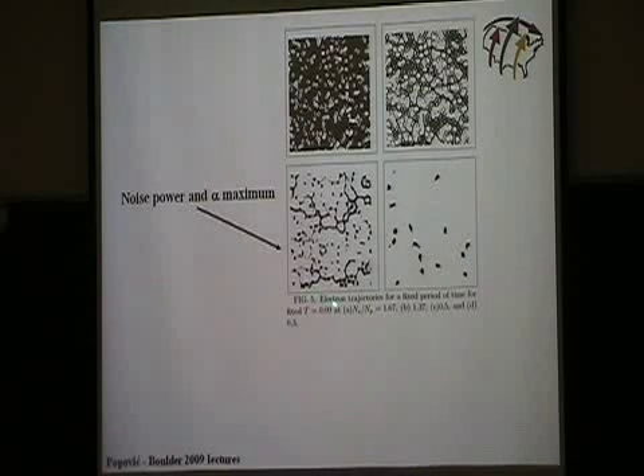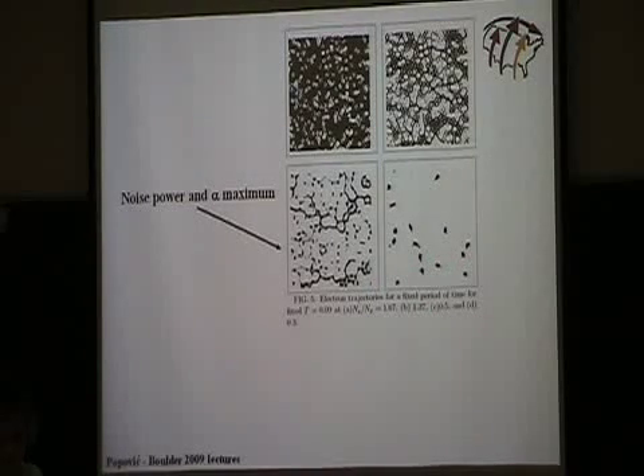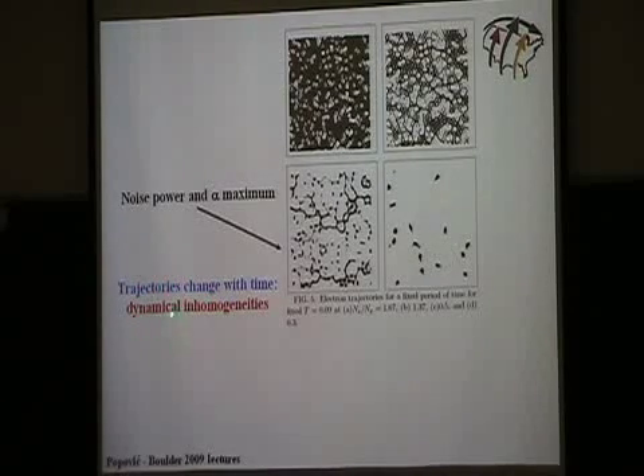And as those of you who work on such things know, they can obtain, if you look at electron trajectories for a fixed period of time, so this corresponds to the case when you have a high density of electrons. You can see that electrons can more or less move freely throughout the sample, except that some may get stuck for a while somewhere, but essentially they can flow easily. As you reduce the density, this splits into a kind of mixture of 2D, 1D paths. And at even lower densities, the motion is mostly through 1D channels. Other electrons get stuck somewhere in the sample, and then at the lowest densities, electrons are localized. So it's easy to see from here why the noise is big. Here you basically have two channels that percolate through the sample that determine the conductivity. So if one of them shuts off, there will be a huge change in conductivity. This is why the noise is big. And of course, this is done for a fixed period of time. If you look at some later time, the picture looks different.